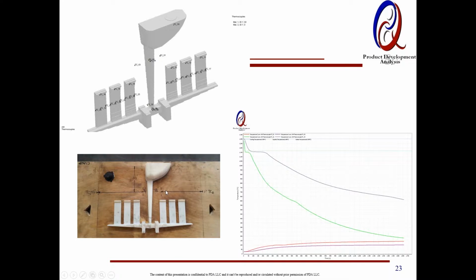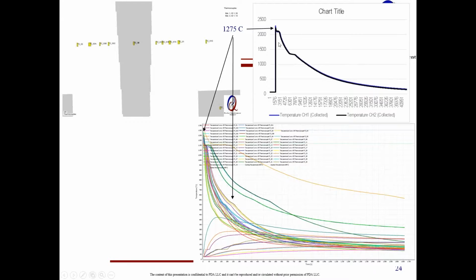Again, modeling simulation is based on the data, and you need to calibrate. So, when we poured these castings at a small foundry, part of our team, we instrumented with thermocouples, positioned at the known locations, and captured temperature time, recorded, and we got a good match. We thought we were pouring at 1300.